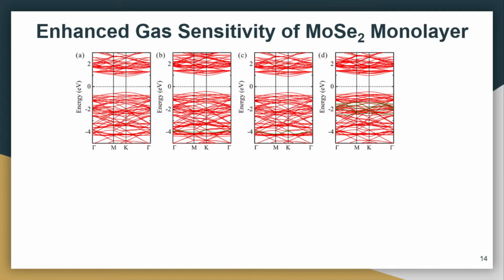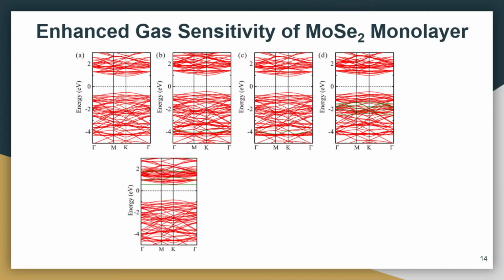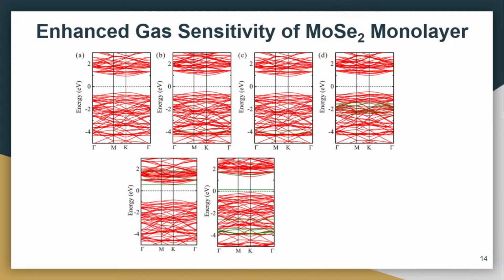But when you go to the NO and NO2, you can see that the band gap changes enormously. It's like the conduction band minimum is around 1 electron volt here, right? But here it's very much less compared to these materials. Particularly here you can see that for NO2 molecules, the valence band maximum just increased.